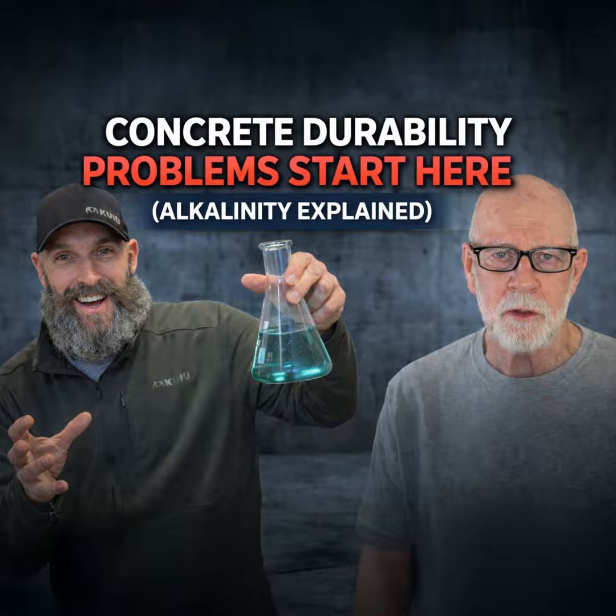As things keep going south, because what puzzled me at first when I saw some of these global studies, there was one in Portugal where it was showing that in the first 2 to 3 weeks after the concrete was placed on a roadway and also a bridge deck, the relative humidity was dropping between 50 and 70%. And they were trying to blame that on the cement hydration. So there's not enough cement in there to create that kind of a condition. It won't use up that much water to drop the humidity. So there's got to be something else. So then when I started looking at calibration salts and everything that salts do, that gave the answer.